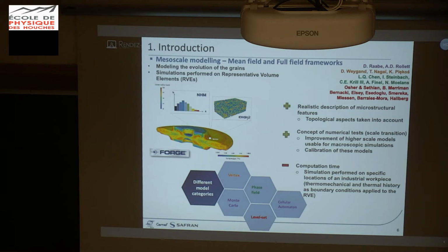And so I will take time this morning in my presentation mainly to introduce level set simulation, which is quite comparable to phase field simulation in terms of capturing description of the grain interface. But where you have a thermodynamic description of migration in phase field simulation, we use a kinetic description for the grain boundary migration in level set simulation. So now, with a bit of history, don't forget different elements.